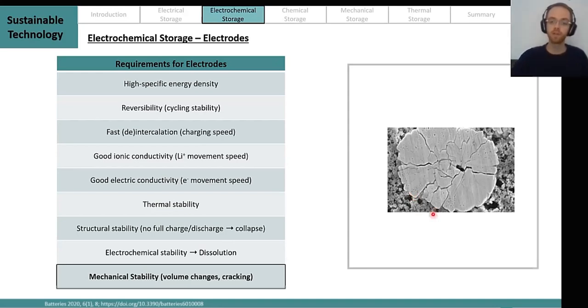particle from cracking apart. You see an electron microscopy picture here of such a battery particle, which is maybe 10 or 20 micrometers wide, and you see that this particle starts cracking after it has been under load and repeatedly charged and discharged. This is something you want to avoid, because once such a portion breaks off, you might lose this part of the material. It might be inaccessible for either electrons or for lithium ions, and each of these will render this part inaccessible and unusable to store any kind of capacity anymore.